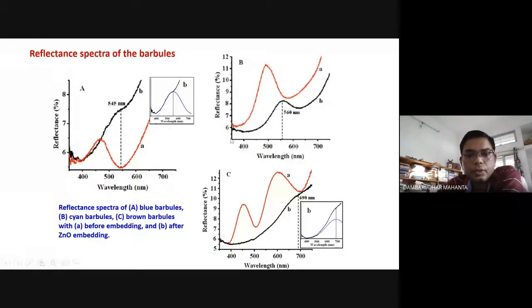So we have three different barbules: in the central region, in the key region, which is blue barbules. The second one is cyan barbules. Third is brown barbules, before embedding and after embedding. So look at the first one, which is the blue barbule. Without zinc oxide loading, you could see here around 460 or so, you have a peak, and then it drops and goes like this. After zinc oxide loading, there is a shift from this position to this position, which is now 545.